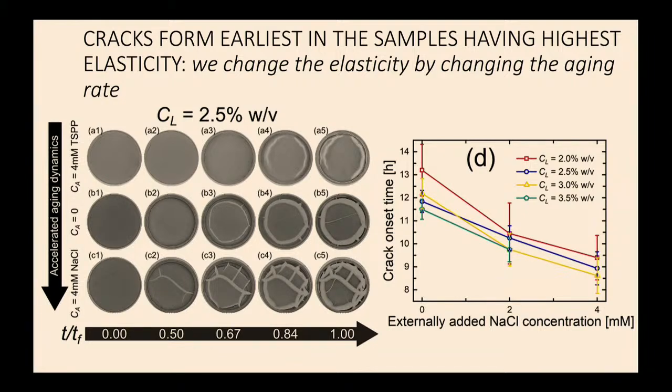So it is a viscoelastic liquid that is evolving into a weak viscoelastic solid, and this is the sample with salt. This is highly, highly elastic pretty much from the beginning, and it cracks a lot, and you can see how different the patterns are. As you become more and more elastic, you have more cracks, and it happens faster, and so on and so forth.